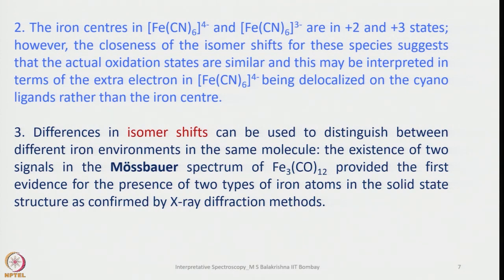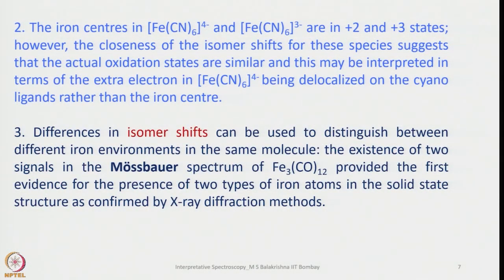And this may be interpreted in terms of the extra electron in [Fe(CN)6]4- being delocalized onto the cyano ligands rather than sitting on the iron center. So this is very vital information. Again, this information comes from Mössbauer spectroscopy. So difference in isomer shifts can be used to distinguish between different iron environments in the same molecule as well. That means not only does it clarify the ambiguity about oxidation state, but it can also tell you about different geometric environments present in a molecule, although simply it appears like they are indistinguishable.